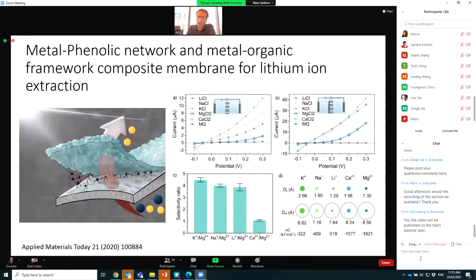And it gives us a lithium-rich feed process. In a series of work, we also tried, as other people have, to use MOFs for separation of ions, particularly lithium ions. But so far, we and other people have reached a similar conclusion that there are some issues with MOFs. I guess the most important are scalability, defects, and selectivity. MOFs work very well in separating lithium from divalents, for example magnesium or calcium. However, when it comes to separating lithium from monovalent alkali metal ions, MOFs still need more exploration. There is also the issue of scaling up MOF thin films.